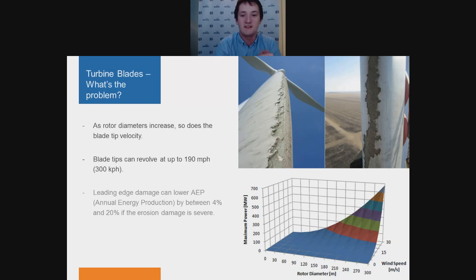Now, the speed of these and the impact of water can cause significant leading edge erosion or damage on the blades, as you can see in those two pictures there. So this damage causes a loss in the aerodynamic efficiency of the blades and then consequently a loss in production. The effects of this can be seen after as little as 2 years sometimes, and the main effect is obviously this lowers the annual energy production. So sometimes this can be as much as 20% if the damage is really severe. You could even argue that it's 100% if the damage is bad enough to cause the blade to split.